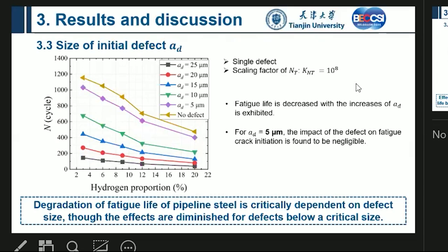The second parameter that we would like to investigate is the size of the defects. For example, if the defects are much larger, you can take a look here, the fatigue life will be reduced very significantly. Here, no defect, and these defects will be 25 micrometers. And we also find here if the defect is very small, for example, like 5 micrometers, the impact is negligible.